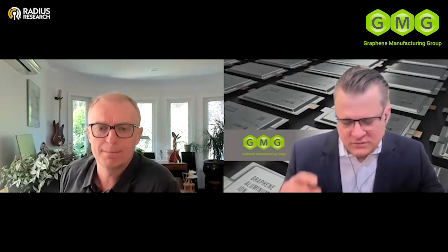What we see is we reduce the wear, and the graphene tends to fill into the metal deposits, which enables us to reduce the friction. We also reduce friction just because graphene is obviously graphite, which is a big lubricant of its day. And we're obviously smaller, about 1,000 times smaller.